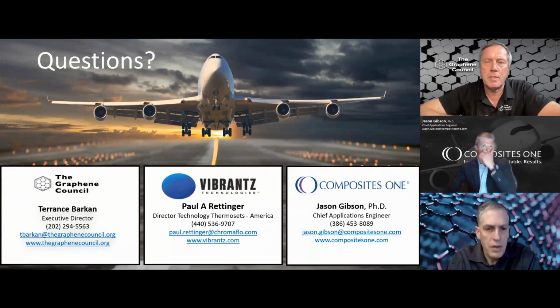So we tested 15 different types of graphene in the original test, and that included a graphene oxide, a reduced graphene oxide, a functionalized material, graphene nanoplatelets, few layers, so something like 3 to 5 layer, as well as 7 to 10. We've not disclosed the names of the companies and the actual materials, but in general, we're looking at a material that's less than 10 layers. Graphene nanoplatelet was the type of material, and another one that performed well was a functionalized graphene material.